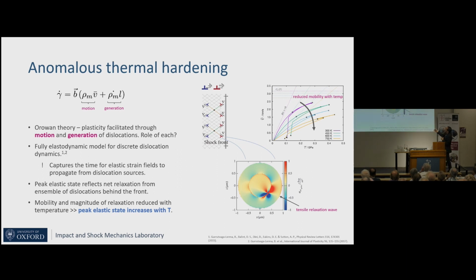And the relaxation that we actually see in the shock front is due to the superposition. Basically, all of these wave fronts, as they arrive at the shock front, they will mediate that stress, and we'll finally be able to measure the dynamic yield strength of the material. And what we found is by increasing temperature, it actually takes longer for those waves to get there, so this is why it was relaxed less. And so there's this counterintuitive interplay between temperature as well as strain rate.